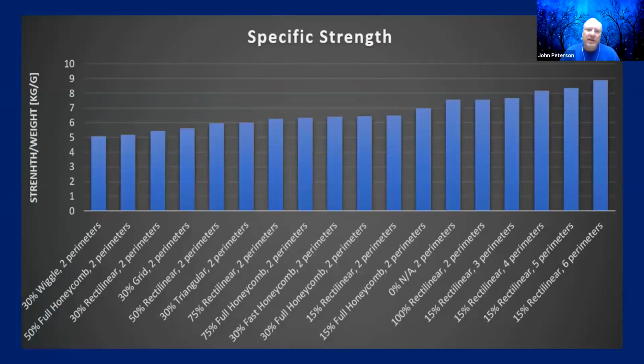You can see he did a lot of testing, and there's a lot of results here. And you can look through that, and you can kind of see some of the weaker ones have almost complete infill, yet some of the stronger ones have only 15% infill. They just increased the perimeters on them. So even he's tried out obviously a couple of different variables just to see if there's any interaction between them. But it's clear that, again, perimeters are more important than infill.